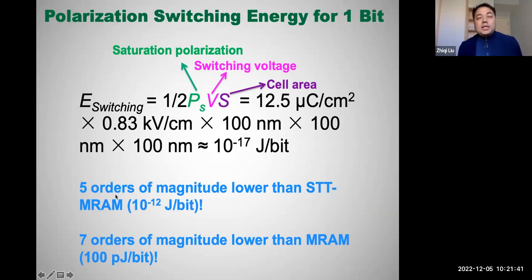If we try to calculate the energy consumption for such a memory cell, we can get a value of around 10 to the minus 17 joule per bit. It's like 5 orders of magnitude lower than the STT-RAM, and 7 orders of magnitude lower than the MRAM. That's all because of the suppression of the Joule heating.